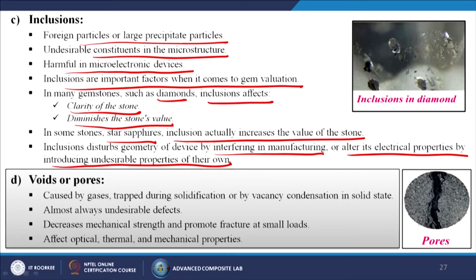Then next one is voids or maybe the pores. So, caused by gases trapped during the solidification or by vacancy condensation in the solid state. Yes, of course, because when we are heating that material, then the material is changing its phase from solid to liquid, and when it is liquid, the liquid metal has the affinity to absorb moisture or maybe oxygen or hydrogen gas from the environment itself, and that will be trapped inside the molten metal. Then at the time of solidification that trapped gas, by increasing the volume, will make a crack and come out and create a hollow space inside which is known as the pores or maybe the voids.